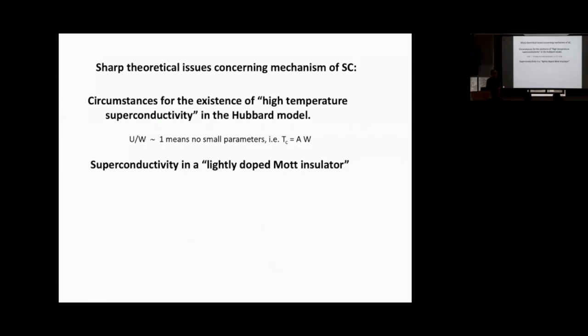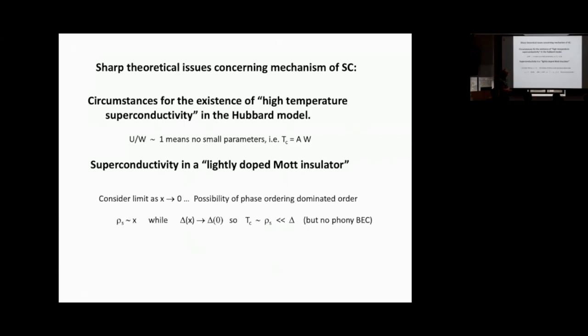And then one other issue is, can we get superconductivity in a lightly doped Mott insulator? That is to say, can we find a case where superconductivity persists as the doping concentration goes to zero? At the same time, this would suggest that maybe we'll find a regime where the superfluid density is parametrically small in proportion to the doping concentration, while the pairing scale is somehow inherited from the insulating phase, so that one will get into this interesting regime, which does seem to be observed in the cuprates, where TC is of order the superfluid density, and the pairing scale is larger than TC and not anything to do with Bose-Einstein condensation. Yeah. I have a question about the first point.